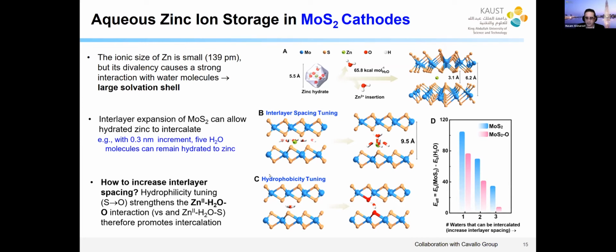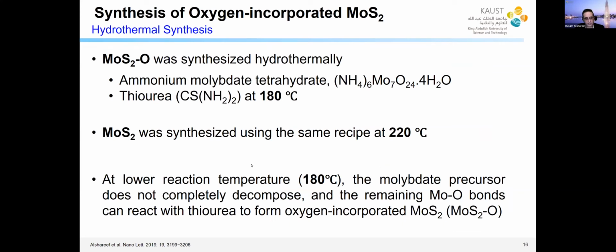Let's see how that affected the material. First of all, how to make this oxygen substituted molysulfide? Very simple, hydrothermal synthesis. Of course, we tried different chemicals, but this ammonium molybdate tetrahydrate, if you react it with thiourea at 180 degrees C in an autoclave, you can actually form this oxygen substituted molysulfide. At 220 degrees C, you get only molysulfide. I will show you in a minute. Why is that? Because at lower temperature, the molybdate precursor actually does not completely decompose. So you retain some molybdenum oxygen bonds when you do 180. At 220, you don't retain many of these bonds. But because you retain these bonds, when you react with the thiourea, you can continue to have some of these bonds and you end up with the oxygen substituted molysulfide.